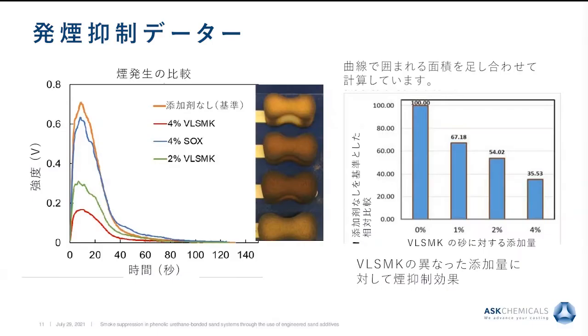So let's look at some real data. We analyze 4 samples. I'm showing the picture of each of the pyrolyzed dog bone specimens at different conditions. We have a control sample, which is the no additive. We always have that there for comparison. We have 2 levels for the dual engineered sand additive, VLSMK, 2% and 4%. And we also add a commercial sand additive just to have another comparison point.